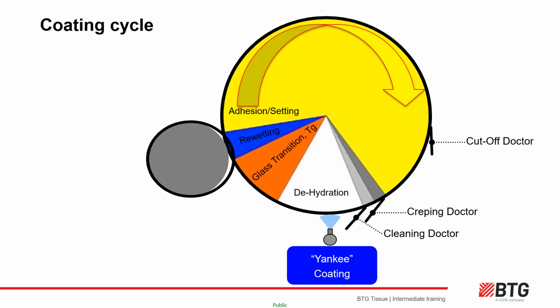Now we see the Yankee applied coating cycle as it plays out on the Yankee cylinder. In this instance with 3 doctors and a suction press roll configuration. The first zone after the coating is applied via the spray bar is the dehydration zone, where the spray carrier water is evaporated by the Yankee surface heat to leave behind the coating mixture in a micro layer on the cured coating above the Yankee surface. The glass transition zone is the area on the Yankee where the adhesion aid or base coat transitions from a fluid liquid through a tacky phase before solidifying. Each polymer having different and quite wide-ranging glass transition temperatures.